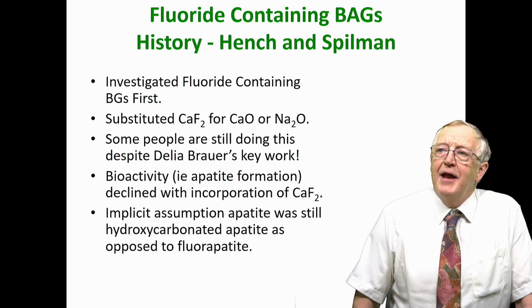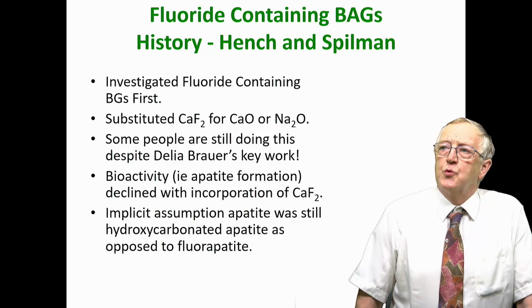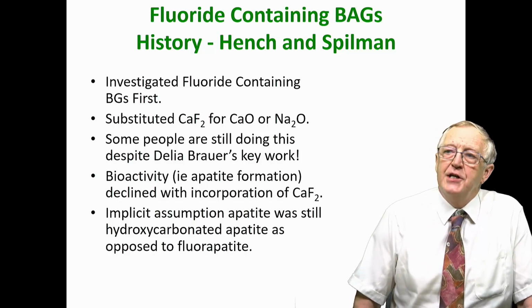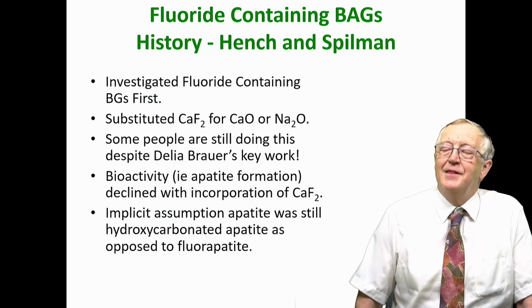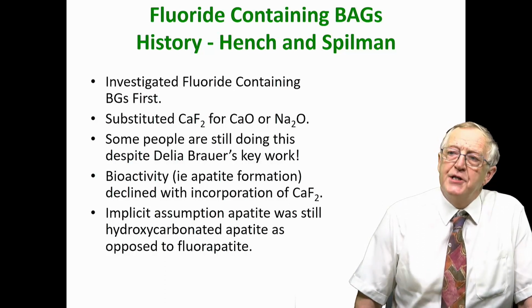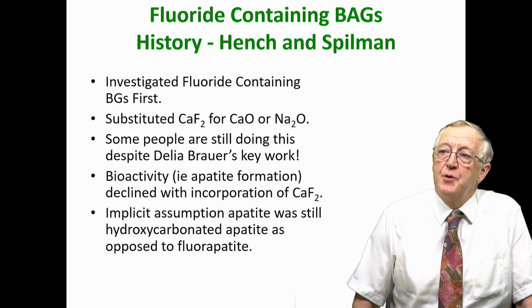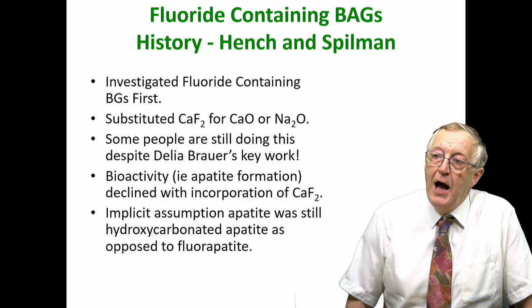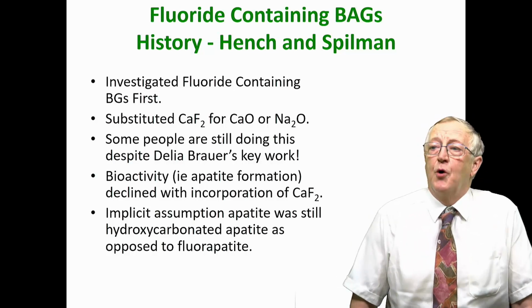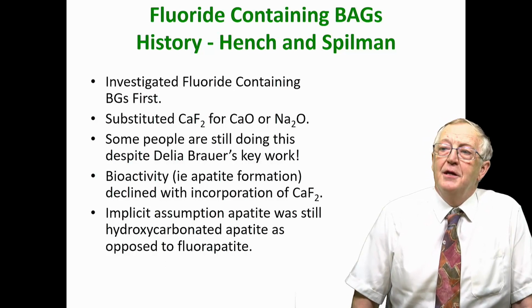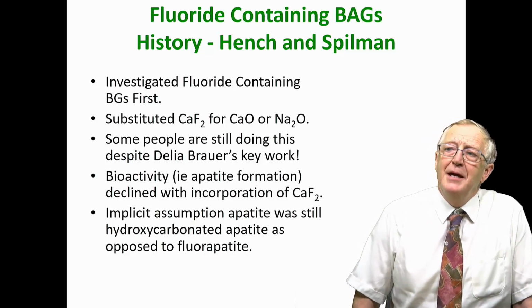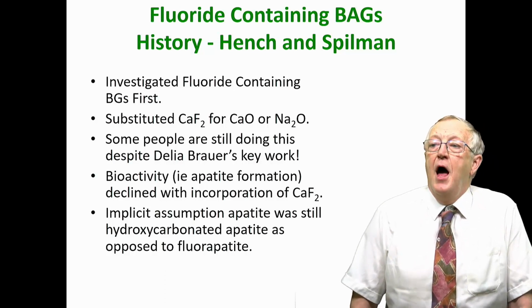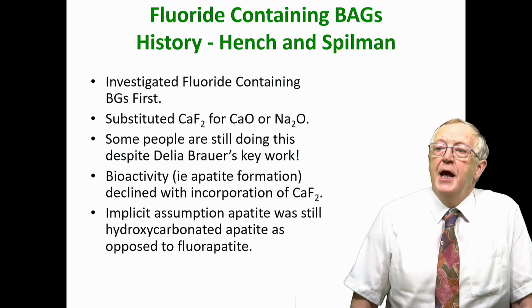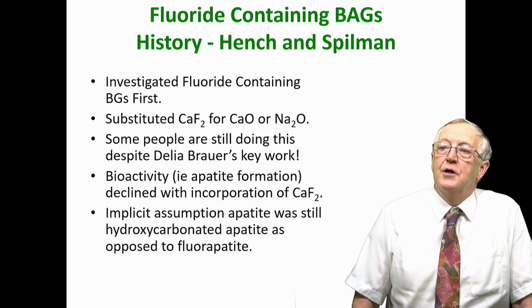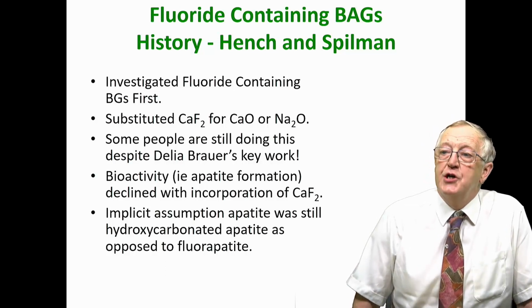Now, Larry Hench and a student called Spilman actually investigated fluoride-containing bioglasses back in the late 70s. But they substituted calcium fluoride for calcium oxide or for soda. And some people are still doing this despite Delia Brauer's work. If you do this substitution, you impede or inhibit the formation of the apatite because you cross-link the glass. And what we do is essentially add calcium fluoride without changing the network connectivity.